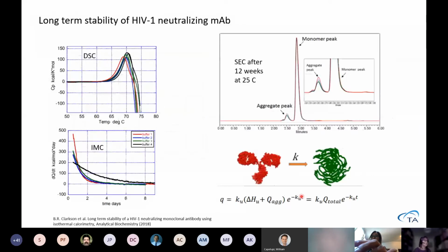We have a real example as well with a monoclonal antibody, where they have screened for different buffers. We can see that all buffers in the DSC, they will aggregate immediately after unfolding. Then they could put it in the microcalorimeter at temperatures slightly below when the peaks start, and we can see the different buffers. With the different buffers, this monoclonal antibody will be different. Now we can see also that we don't have the endo-exothermic, because this is a reaction that happens simultaneously. So we actually see more of the endothermic reaction here compared to the exothermic aggregation here.